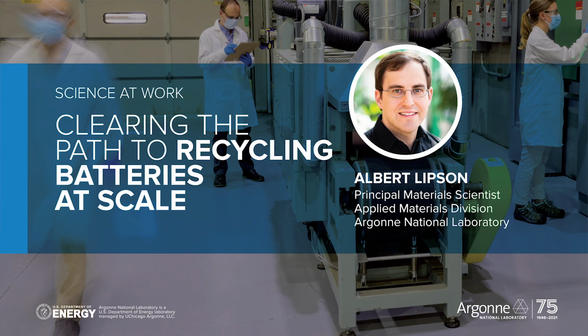So once the batteries are shredded, the next step you need to do is to be able to remove the electrolyte material. This electrolyte contains flammable carbonates as well as the electrolyte salt, which is typically lithium hexafluorophosphate or LiPF6. So we get this off currently by simply rinsing in a carbonate solvent. We're then able to take the rinse out from that and then concentrate the rinse. And you can actually regenerate a working electrolyte from that concentrated electrolyte.